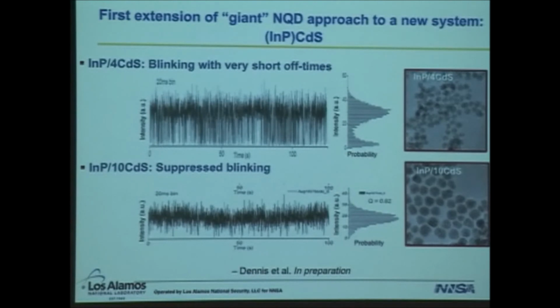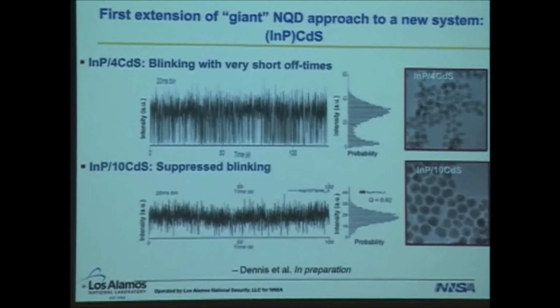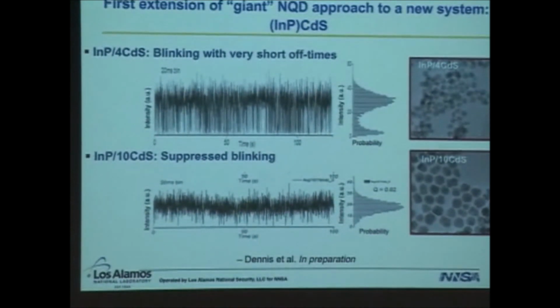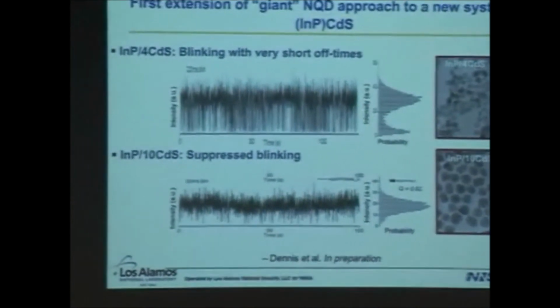Yeah. So if you could comment a little bit further. From your results, I guess the conclusion on the suppression of blinking, would it be fair to say that this thick shell just prevents the core from spurious charging? That's certainly an aspect. So it's actually a second paper that's now in submission. The paper I referred to that's coming out in Nature, we limited to, I think, 7 shells. So I wasn't explicitly looking at the giant dots. We kept 7 because they were stable enough to do the spectroelectrochemistry technique, but we still had blinking behavior to look at.